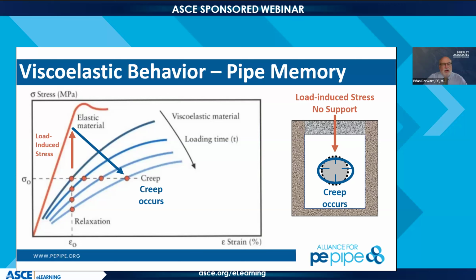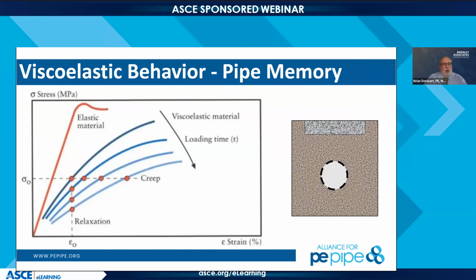So if you have a constant load on it over time, it's going to continue to move until it can balance it. And that's what these different curves show: as you increase the amount of time, the creep has more and more effect. In other words, it stretches more. That doesn't necessarily mean the strength has changed, or that the modulus under the elastic portion has changed. However, the modulus for your design, you have to take into account the creep factor. And that's what this chart shows. You treat it differently than you would an elastic material. The whole idea is understand the material, design for the properties of the material, and you'll be fine.